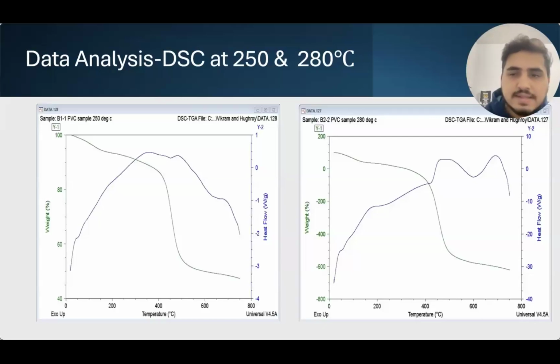As we can see from the graph, the sample at 280 has a lower residual weight, around 10%, compared to the one at 250, which has somewhere around 40%, indicating more complete degradation. Exothermic peaks during the deterioration and the moisture loss at the lower temperature were seen in both samples, and PVC didn't experience any mass increase during oxidation like coal does, which indicates a different combustion process and decreases the chance of spontaneous ignition.